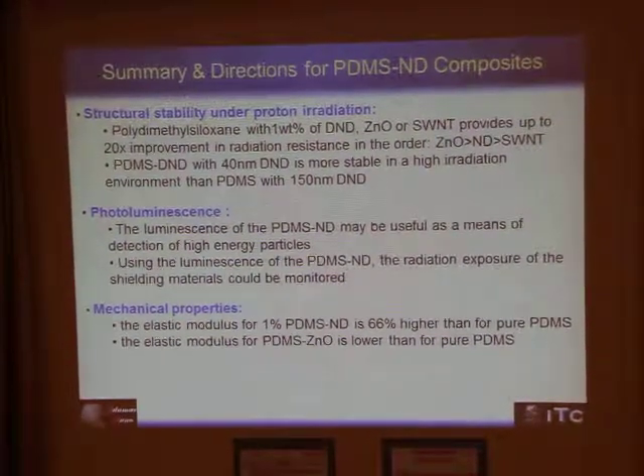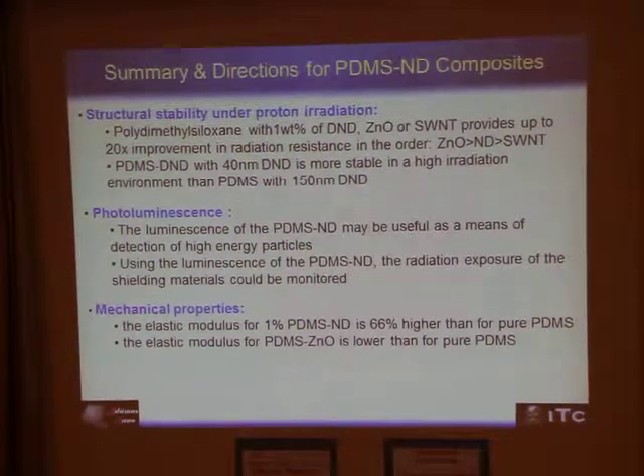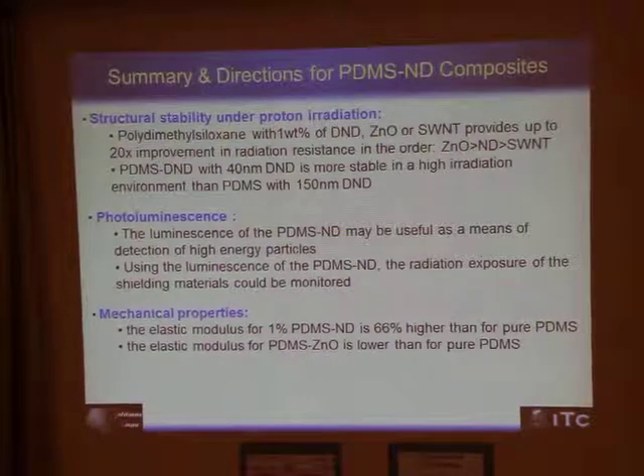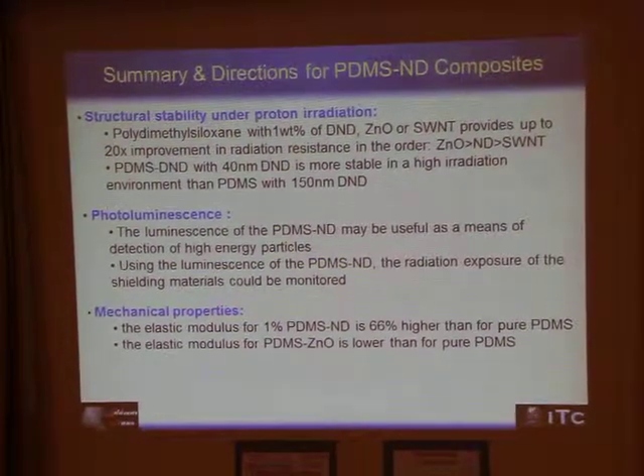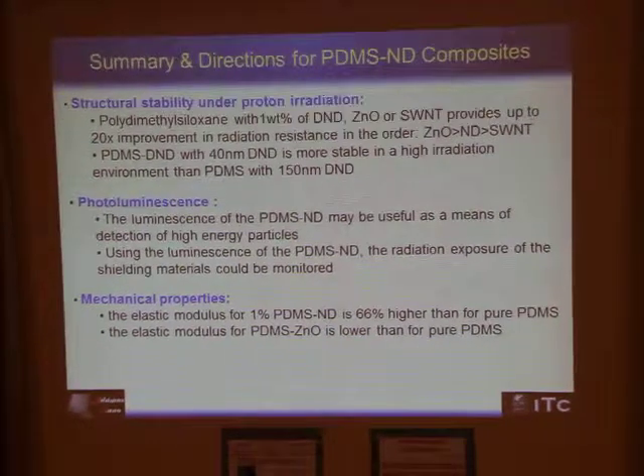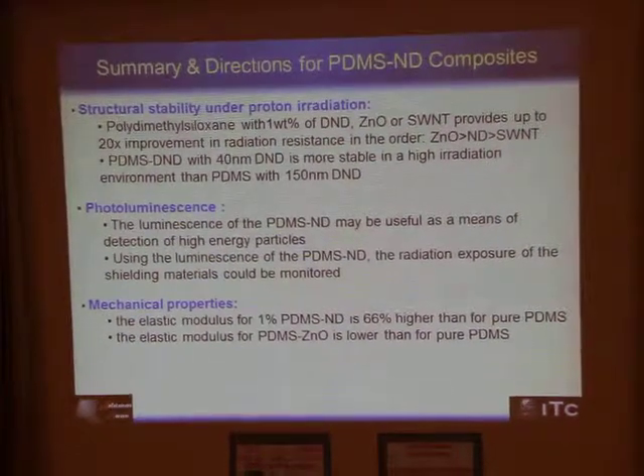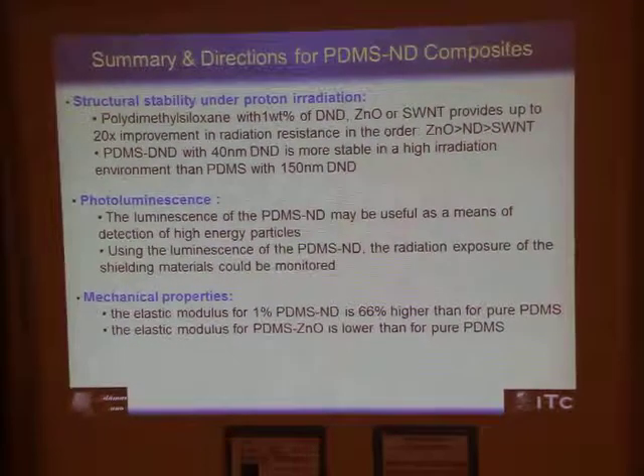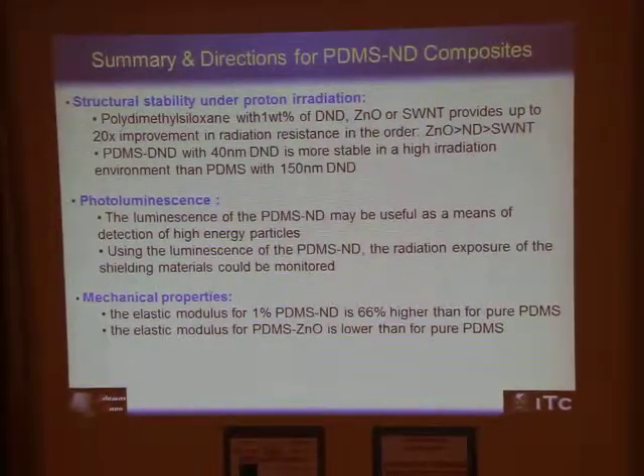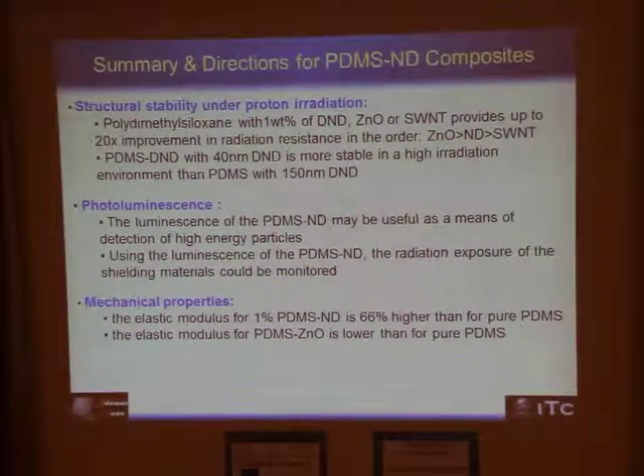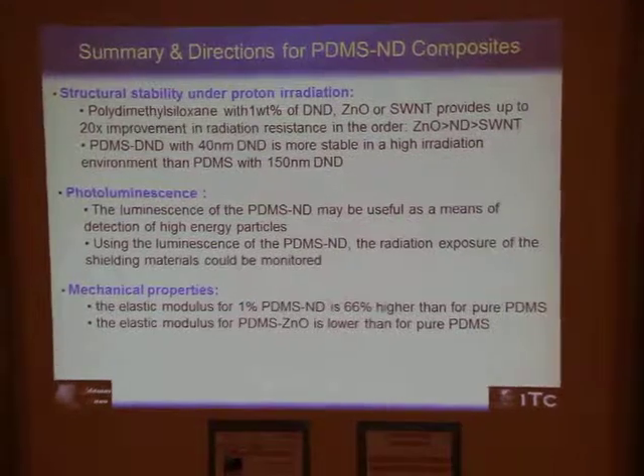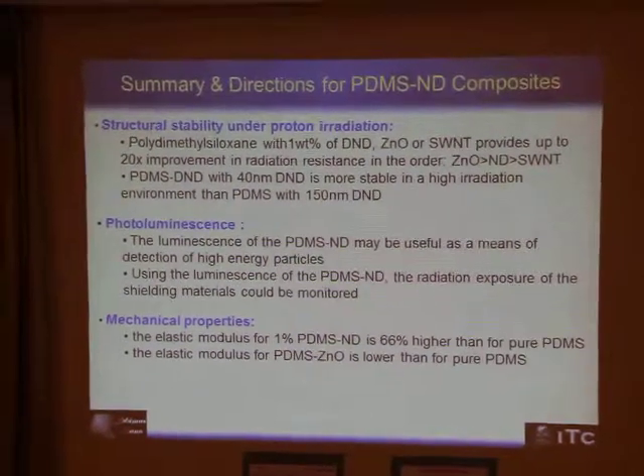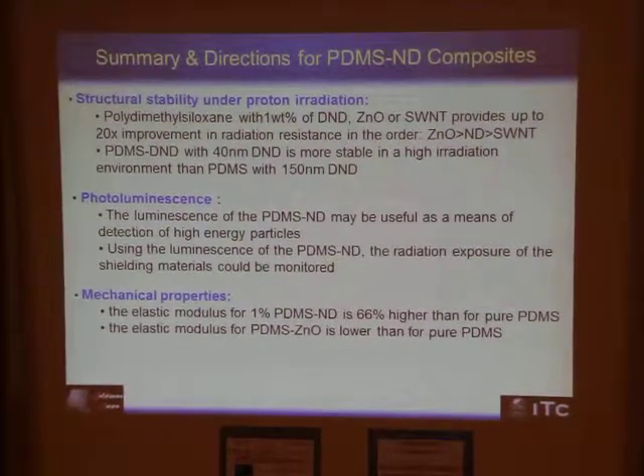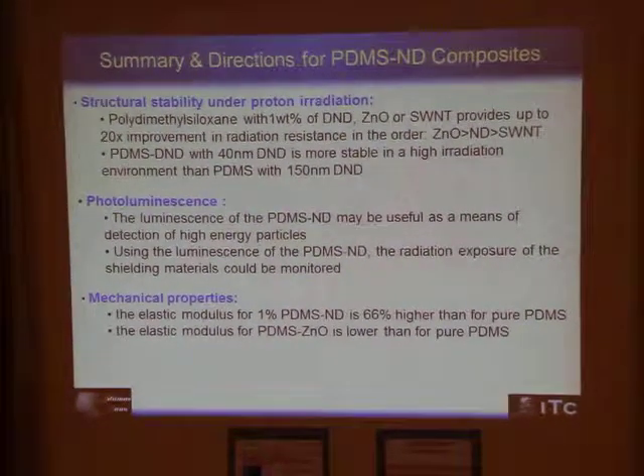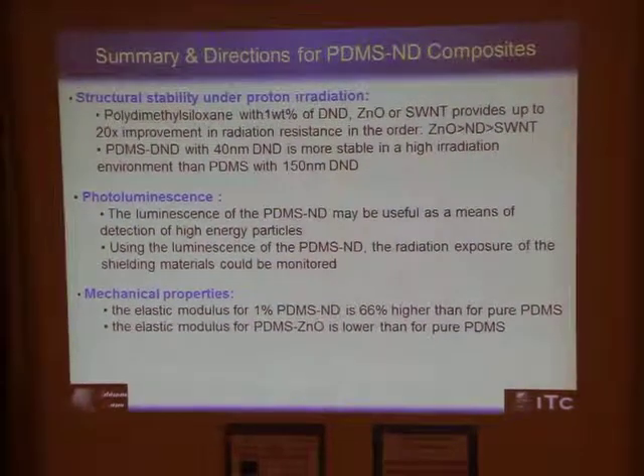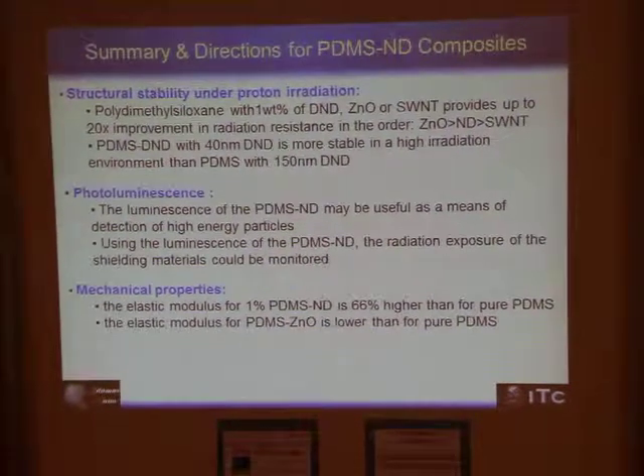In terms of luminescence, PDMS nanodiamond composite can be a useful means to detect high energy particles in general, as well as possibly detect irradiation dose to provide calibration of photoluminescence corresponding to some specific doses. In terms of mechanical properties, nanodiamonds provide significant improvement of the mechanical properties of PDMS, while zinc oxide does not. So you can think of the combination of improvement of radiation resistance and mechanical properties as in favor of using nanodiamond particles.